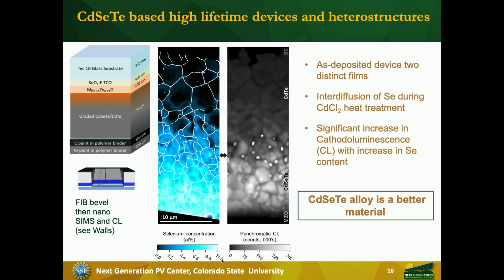Now, one of the recent findings is that when you add selenium to cadmium telluride, it improves the lifetime. When you see a bright cathodoluminescence, it means that the defects have been somewhat mitigated. So this region corresponds to that region right there where there is more selenium. And then there is tellurium at the back, which is cadmium telluride here.